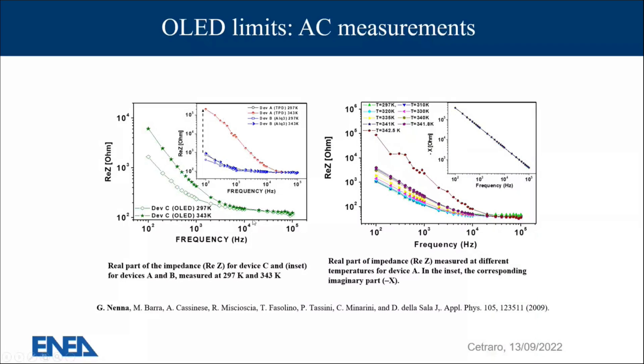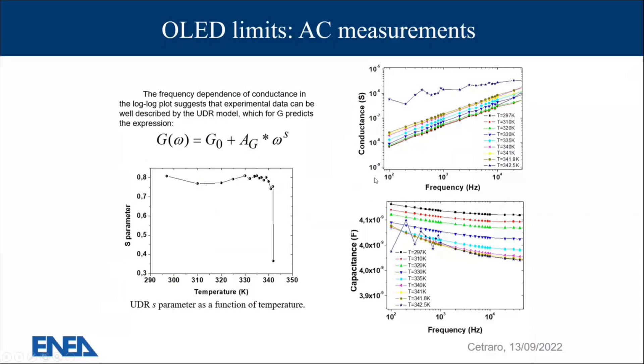We can see the real part of the impedance and how it changes with frequency and temperature. We see that the hole-transporter-only device shows very big changes, because it is affected by temperature and so the glass transition. The other device is not affected in the same way. Controlling only the hole transporter and changing the temperature in a more precise way, we see a big difference when we pass through the glass transition region. If we analyze our material using a universal dielectric response model and analyze in particular the parameter of this formula, we can see that the material will fail only at the end of the glass transition region — always over 340 Kelvin.